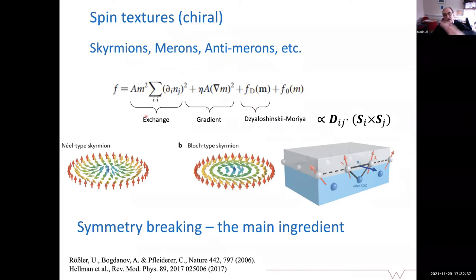So the free energy has all kinds of components which are quite normal, like the exchange effect between the magnetization, a gradient. And then there are second order effects like the Dzyaloshinskii-Moriya interaction, which comes at the interface, in this case due to the canting of the spin, given by the spin orbit coupling. And there is a vector, the Dzyaloshinskii-Moriya vector, which will push this rotation of the magnetization.